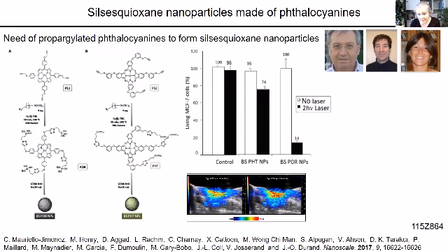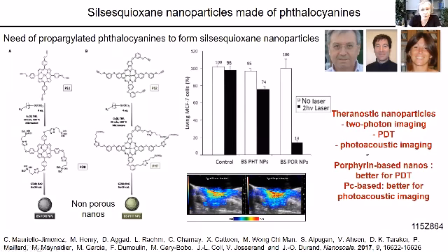They have been tested also in photoacoustic imaging, and the results were beautiful. But when we were checking the photodynamic therapy with 1 or 2 photon excitation, it was not that good. So the conclusion was that we have systems that are theranostic. We could make some 2 photon imaging, but anyway, the porphyrins were better. As a phthalocyanine enthusiast, I didn't like that much to hear.